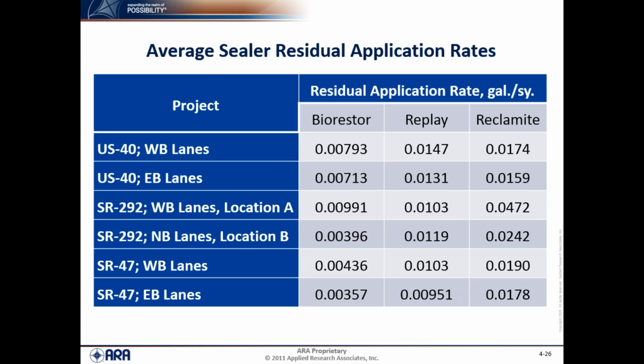I will come back to these rates later on, especially when we start talking about the data analysis of the test results. But this just shows in each of the lanes, again, the US 40, State Route 292, locations A and B, and then the State Route 47. Key thing to note here is that the Biorestor generally had the lower residual application rates, then followed by the replay material, and then the Reclamite supplier had the greatest residual application rate placed between all of the projects, all the test sections, consistently.